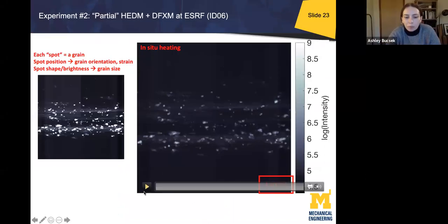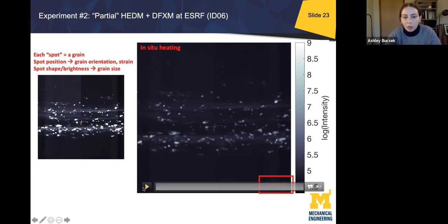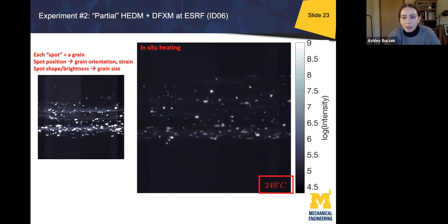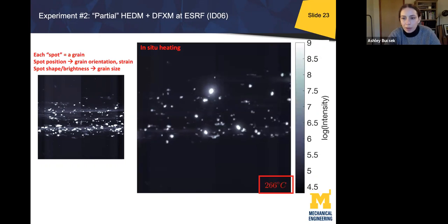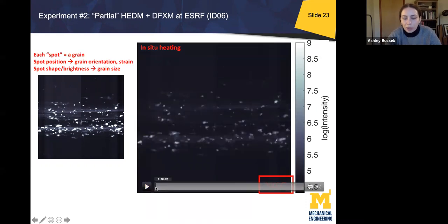Yeah, it's both. The sample was rotating a little, and so John did do some corrections to keep it centered to where we had it initially. But you could also see there are certainly individual movements at pretty low temperatures, like in the first or second and third measurement that we took. These grains are rotating, and we know that they're rotating because only certain reflections are moving, not the whole sample.